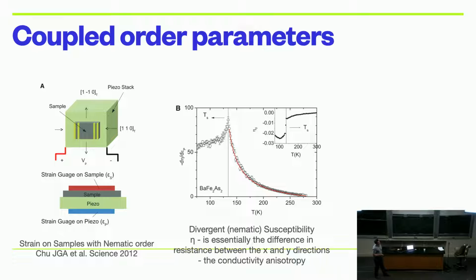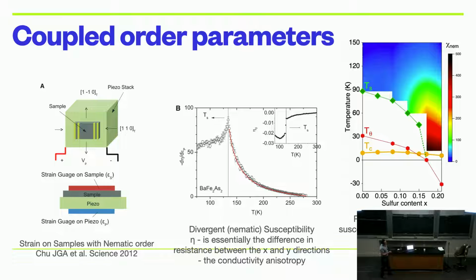Other people picked up on this and started to study lots of different kinds of materials, iron-based superconductors, orthorhombic systems, lots of kinds of things. And we often publish things that look a bit like this. This is known as a phase diagram, where this particular group from Shibachi's group in Japan were changing the sulfur content of a particular iron superconductor, and they could see the nematic transition drop down to zero. But then what this color plot shows is essentially the magnitude of this nematic susceptibility, so basically how quickly this curve diverges. Where you see the red color is where it's diverging very fast, where you see the blue color is where it's diverging very slowly.